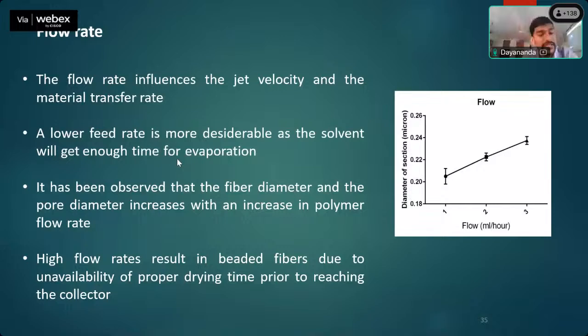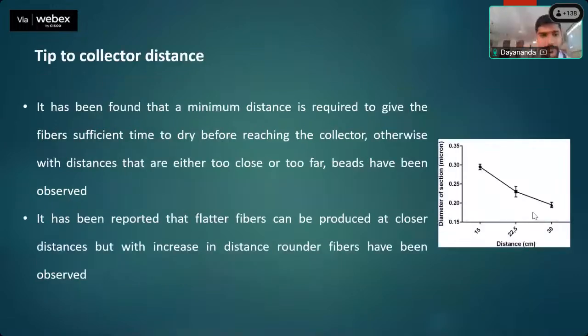The tip-to-collector distance also has to be fixed in the beginning itself. Generally we maintain 10 to 15 centimeter distance from the tip to collector. This distance is required to give fibers sufficient time to dry before reaching the collector. Otherwise, if the distance is either too close or too far, bead formation has been observed. It has been reported that flatter fibers can be obtained at closer distance, but with increase in distance, rounded fibers have been observed.